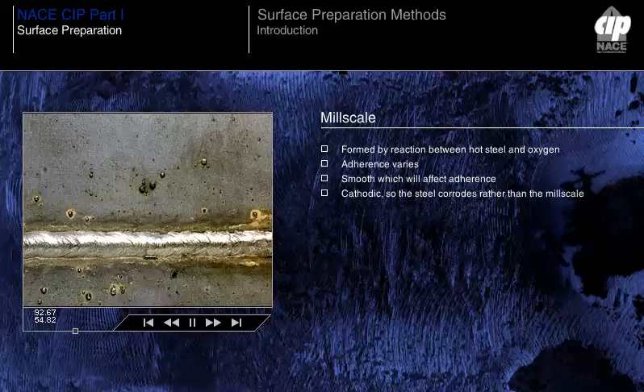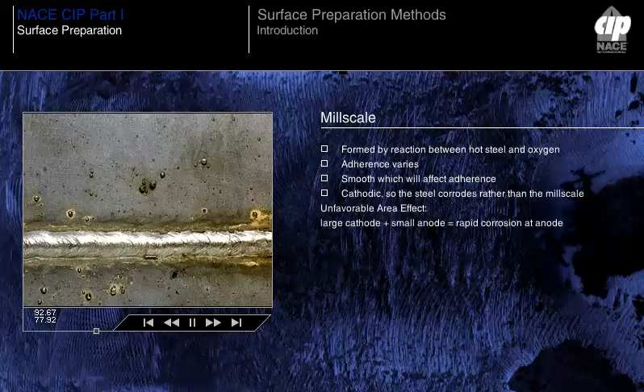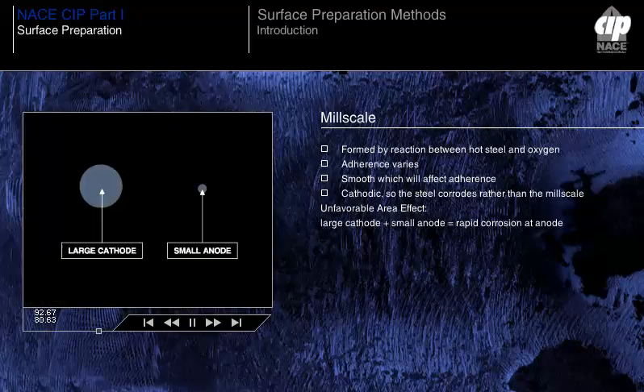Mill-scale is cathodic relative to bare steel. When steel is partially covered in mill-scale and exposed to corrosion, the cathodic mill-scale does not corrode, being protected by the anodic steel. Corrosion does take place at the anodic surface, and base steel is lost. This effect is the opposite of what is generally required. When most of the surface is covered by mill-scale, corrosion at the anodic areas may be accelerated by the unfavorable area effect shown in the formula.